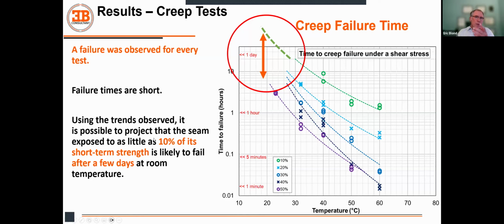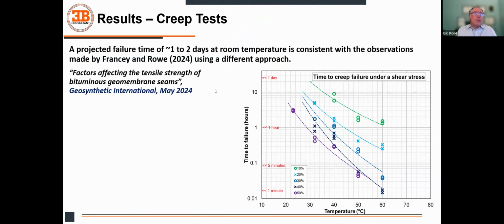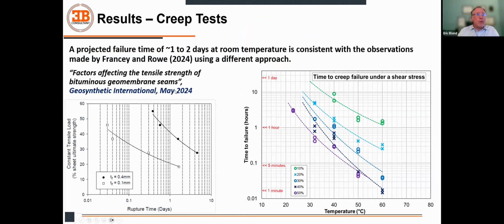So using the trends observed, what we observed is that with a stress as little as 10% of the short-term strength, it just takes a few days at room temperature to break. And that to me was very interesting because I had been working on this project for a couple of months, and eventually I found this paper by Kerry Rowe and his student, Mr. Francey, which used a completely different approach, and they published this paper in May 24. So that was just a few months ago.